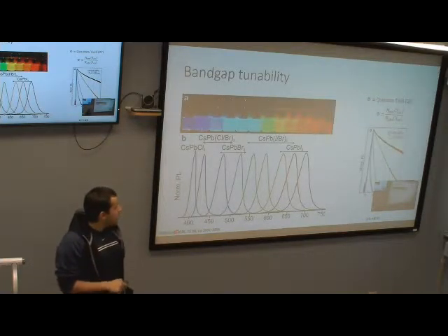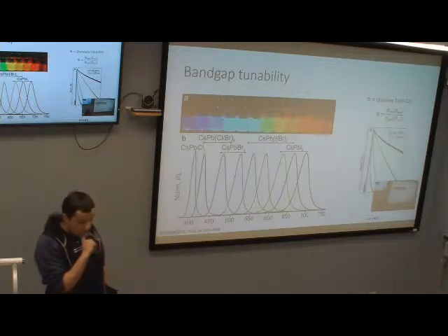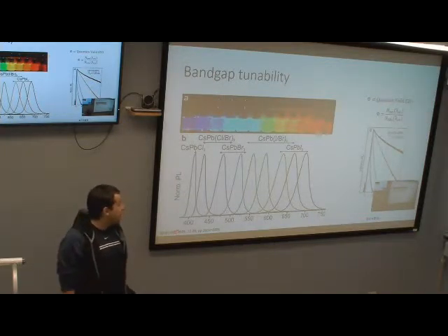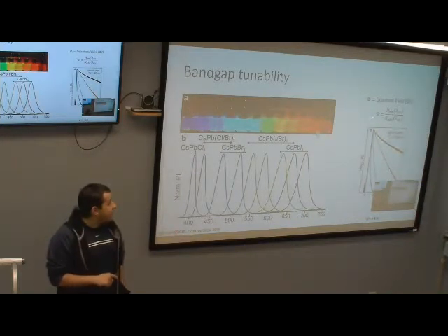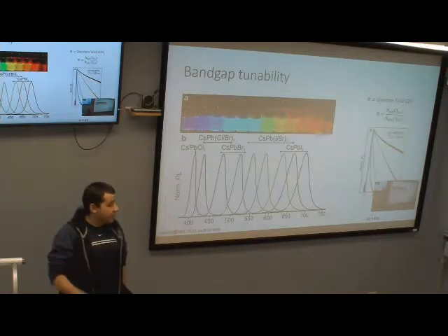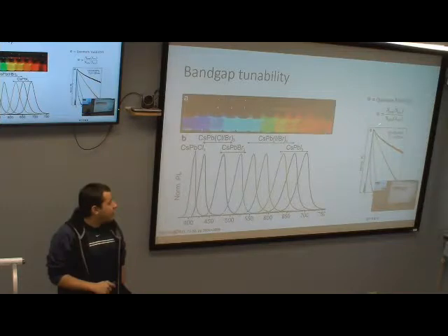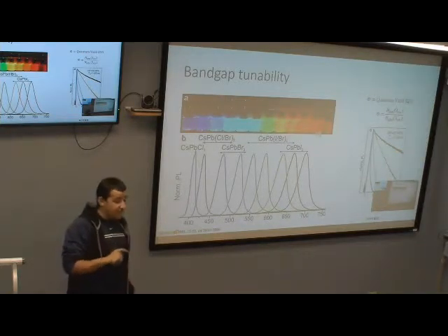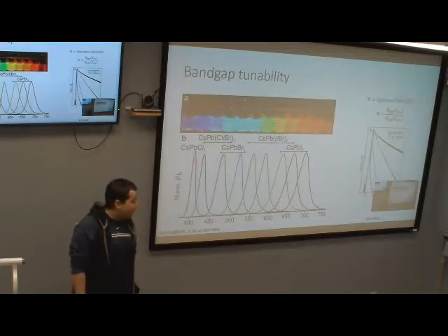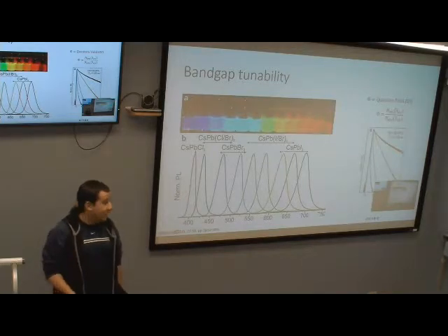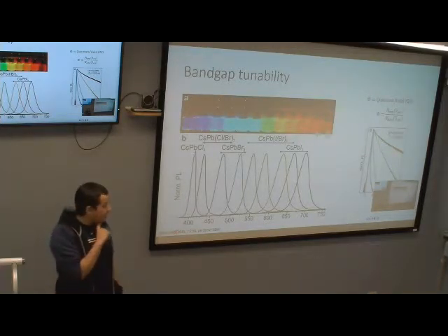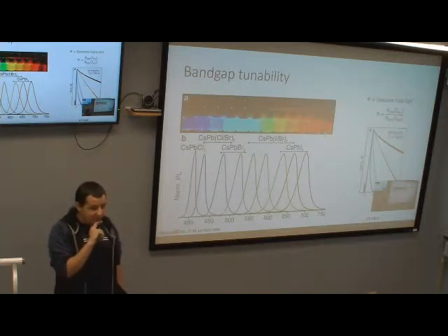And here, when I mentioned quantum yields earlier, these perovskite structures in the colloidal nanocrystal form are found to have a quantum yield of 50 to 90%. Quantum yield is the number of emitted photons over the number of absorbed photons at the excitation wavelength. So it's just a ratio. The higher, the better, obviously. We want to get as much emission as we get absorption.